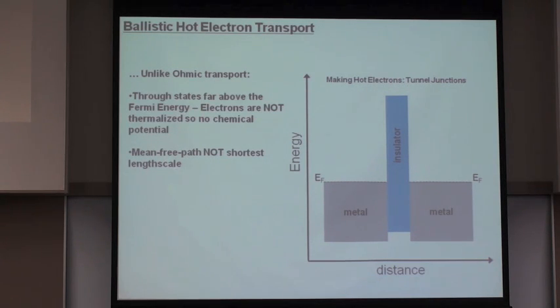It turns out that the problems that I described are really fundamental to any kind of ohmic transport regime. And so the way around this fundamental limitation to spin injection is to use a different injection mode. We use ballistic hot electron transport, not only for injection, but of course later on for detection. After all, you could be injecting spin polarized electrons all day, but you'd never know it. You have to at some point make a measurement. You have to detect the spin after they're injected, move to somewhere else, and then come out of the system.